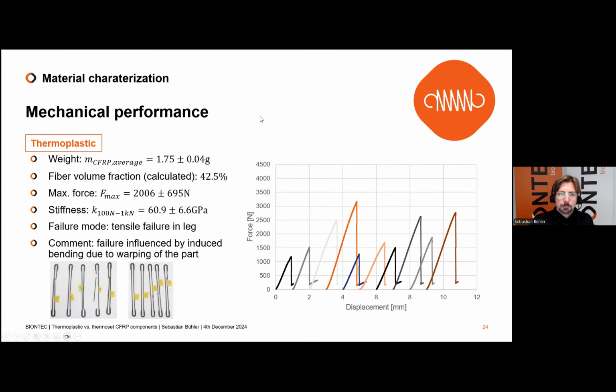For the mechanical performance of the thermoplastic parts, the weight is a bit higher because in the gap here and the edges here, we have more material. Of course, the fiber volume fraction is also a bit higher compared to the thermoset. But the mechanical performance is mainly driven by the stapled yarn, because we have a tension element and not the continuous fibers. Then you see that we have a much lower maximum force, about 2000 Newton, and the stiffness is around 61 gigapascal, so also a little bit lower than with the thermoset and the continuous fibers.